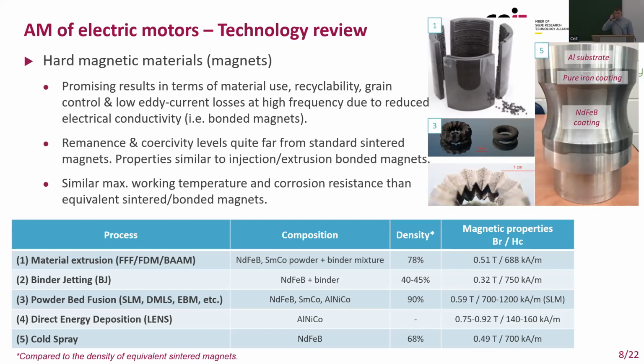Regarding additive manufacturing of magnets, quite promising results have been obtained in terms of material use and recyclability. Also, it's quite interesting that with additive manufacturing, the grain size can be quite precisely controlled, and this allows the material to have a good coercivity without having to rely heavily on rare earth materials such as dysprosium or terbium.